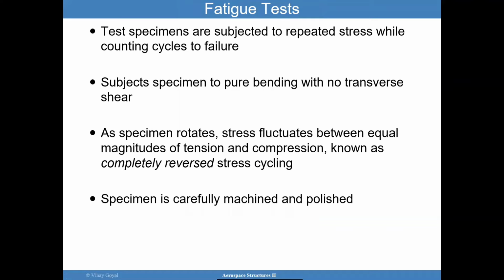So fatigue tests typically subject a sample to repeated stress while counting cycles to failure, subjecting the specimen to pure bending, typically with no transverse shear. As a specimen rotates, the stress fluctuates between equal magnitudes of tension and compression, and that we call completely reversed stress cycling. That's one approach, but you could do it for different types of stress reversals. So maybe you test at 100 megapascal on one end, but maybe less, like minus 30 megapascal, on the other end. If I go from minus 100 megapascal to 100 megapascal, I call that fully reversed. Usually the specimens are carefully machined and polished in this type of testing.